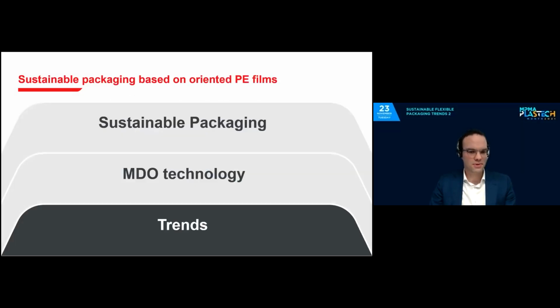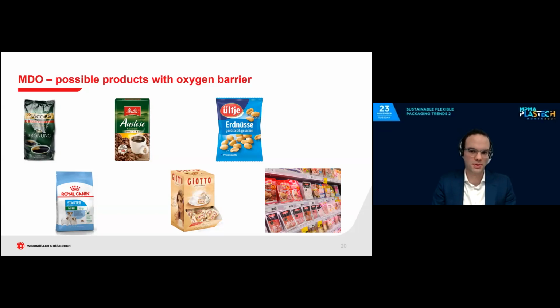What are the next steps and the big trends we see after this development? We have heard it a lot from Bobst about the typical demands of oxygen barrier and water vapor barrier. So in our different testings, we have reached OTR values of below 1 with EVOH co-extruded film with a very low EVOH content inside, because let's assume when you are adding 10 micrometer EVOH in such a film and stretch it 5 times, 2 micrometer are still in the stretched film, and this is very much compliant with the CEFLEX guidelines. Yeah? So these are the next steps.